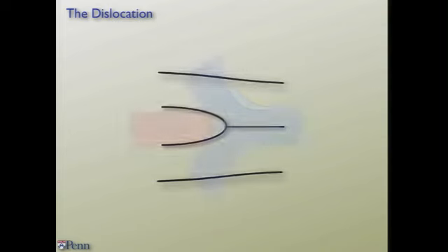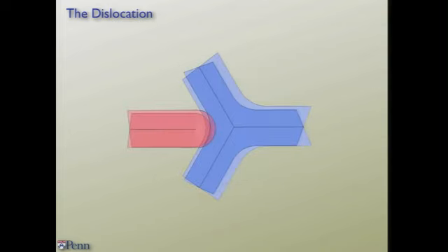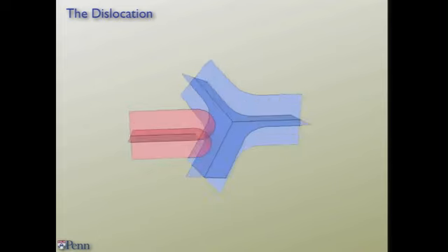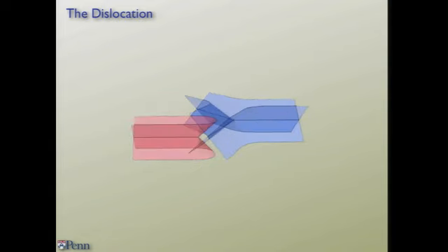This actually is a dislocation. Look, do you see? Here's the -1/2 and here's the +1/2, and the -1/2 hugs the +1/2. But when I turn it sideways, you see the difference. The difference is that to get the +1/2 and the -1/2 to join up in the dislocation, they have to be at different heights. They were at the same height in the last picture. Now they're at different heights.